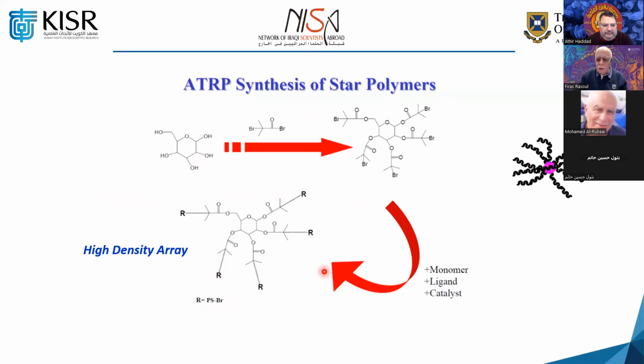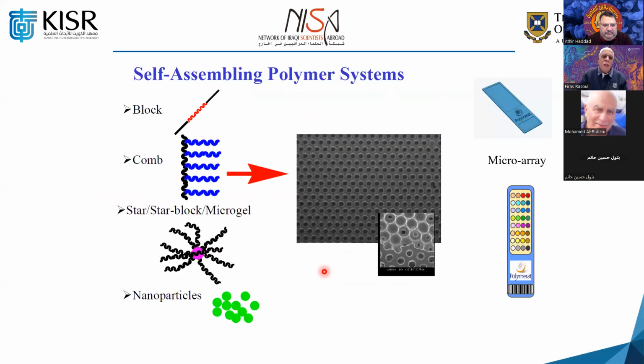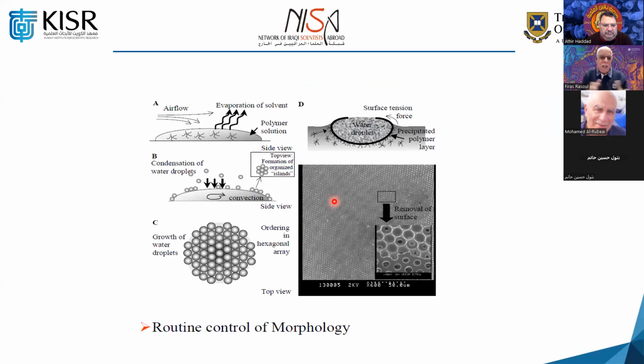And what we found, very, very interestingly, when you bring these stars, or even the block polymers and others, when you dissolve them and you put them on any plastic surface or any surface, even a glass, and you let them evaporate slowly in order to prepare a surface, you find them forming this fantastic, very nice honeycomb structure. And we found an old paper talking about that, actually.